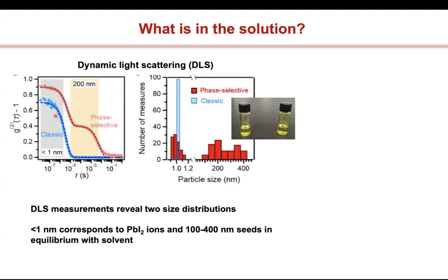So for the classical sample, you see that you get a curve which is a single exponential. And when you extrapolate what the size is of the particles within this, it gives you something of the order of a nanometer or less than a nanometer. And so this is consistent with the size of lead iodide particles that you have. They have a radius of about 0.7 nanometers. And so that was consistent with it.